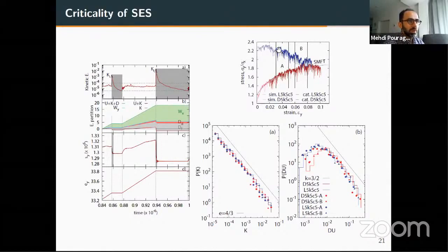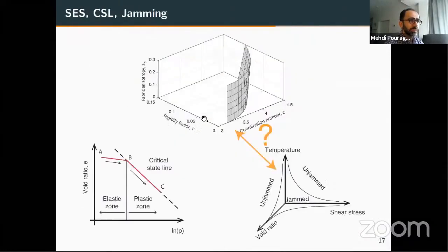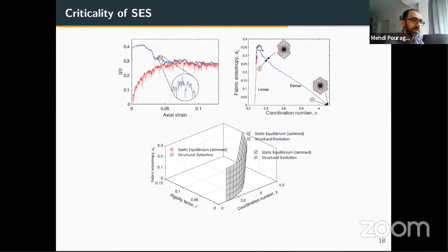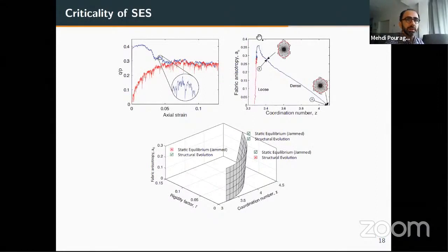Essentially, what we are looking at are two ranges. This is the dense case, this is the loose case, and we are looking at ranges after the peak of stress for dense, when we start to see the events taking place, but before the steady state. And also we have another range B, which is much closer to a steady state. So critical state theory tells us that the state of the two materials is the same only when the critical state or a steady state at the end is reached. The SES, however, if I go back to this picture, tells us that the state is the same before the critical state, when these two lines are aligned.